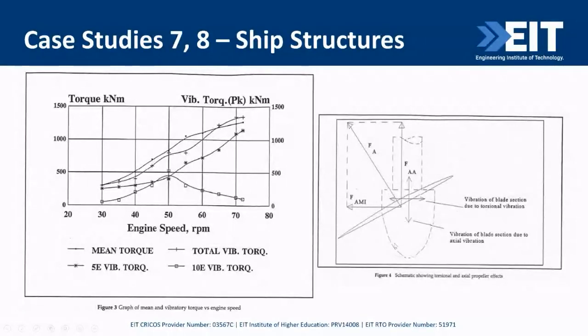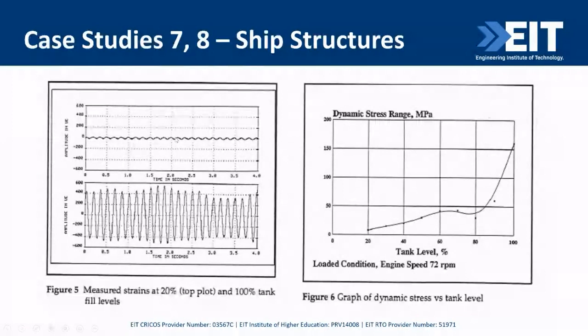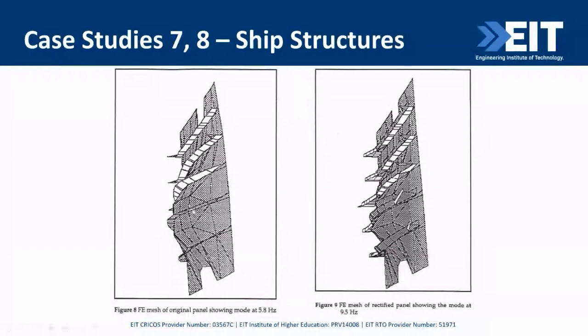so your prop is going around and thrusting, but it's also vibratory, got vibratory motion on it because of the vibratory torque, and it's going back and forth and causing the axial thrust, vibratory thrust. So it's not just mean thrust, it's vibratory because of the torsional vibration. And that was shown as soon as the ballast tanks were full, they went from very low strain to through the roof. And if you look at dynamic stress to speed, it's through the roof with tank level. And that was rectified in Singapore with a stiffening, good gusseting and stiffening as should have been designed initially.